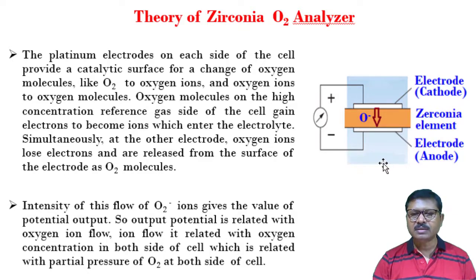Oxygen molecule on the high concentration reference gas side of the cell gains electrons. Say this is the high concentration side, the reference gas side. So on this side the oxygen gains electrons to become ions which enter the electrolyte. So at this position oxygen gains the electron. After gaining the electron it converts to ionic form, and the oxygen ion will pass, according to this figure, from the upper surface to the lower surface. From top to bottom there will be a flow of oxygen ions.